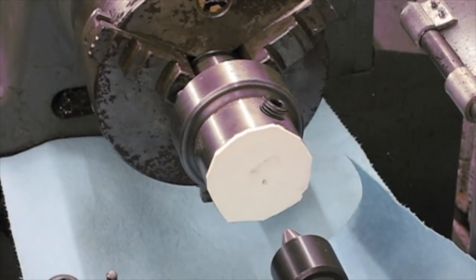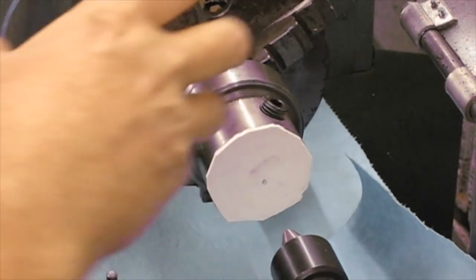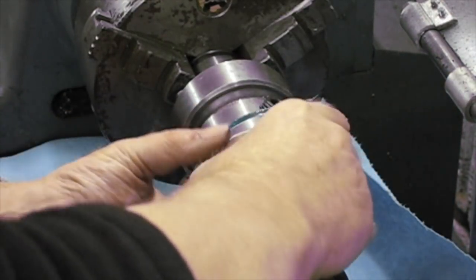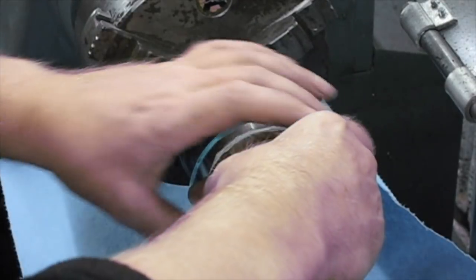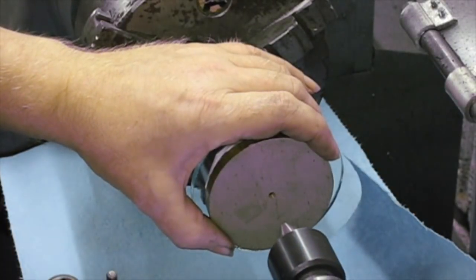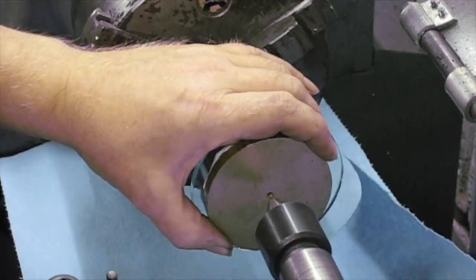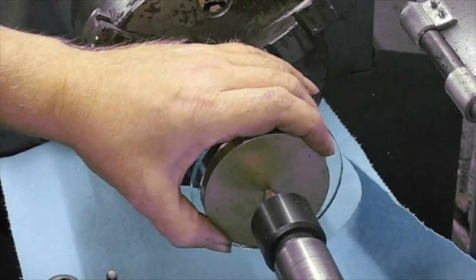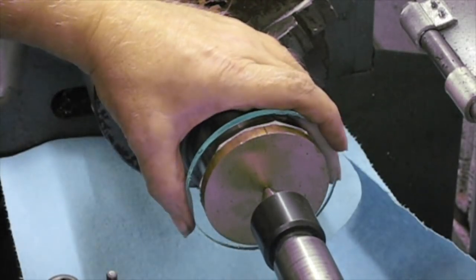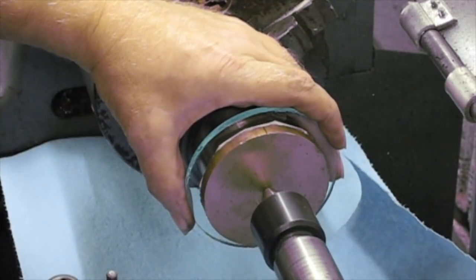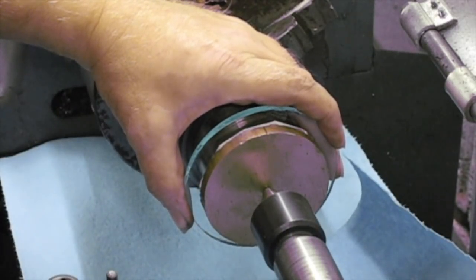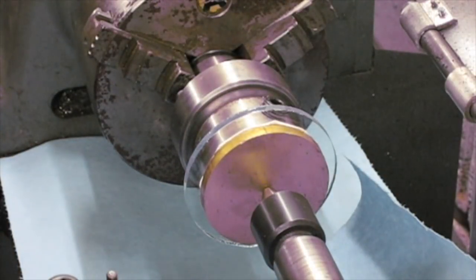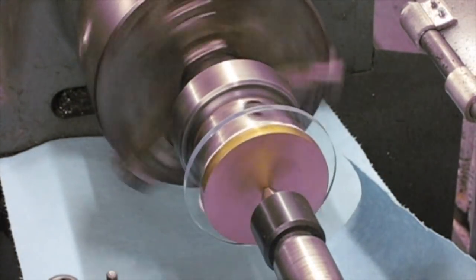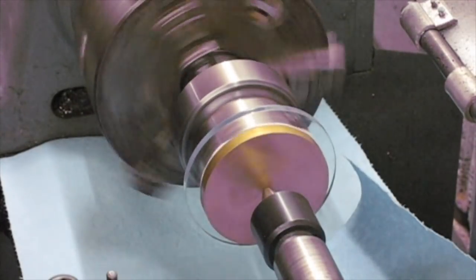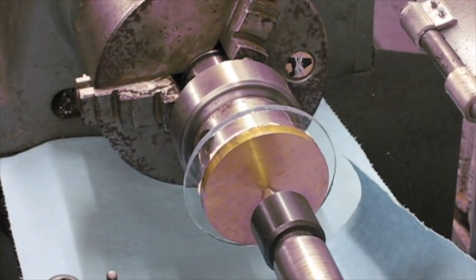Much to my annoyance, the glass discs that I had cut by water jet at significant expense all came out oversize. The manufacturer did say they could only manage a tolerance of plus or minus 2mm, but they all came out exactly the same size at 1.5mm oversize, which means I'm having to grind them down with a diamond file. I'm doing this in my lathe. I don't like doing it because diamond glass dust isn't nice, so I've covered the ways, and I'll vacuum up carefully and do the best I can.